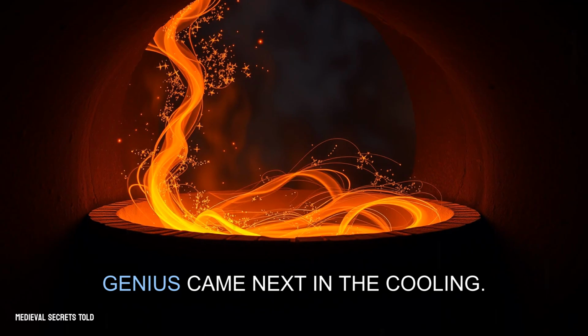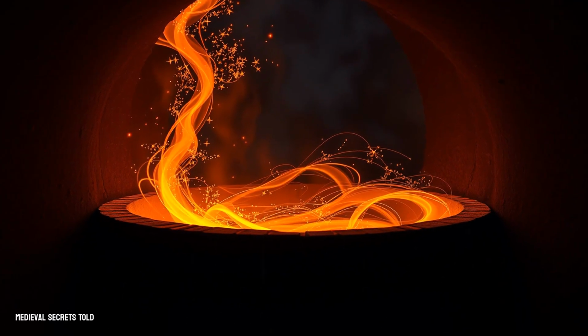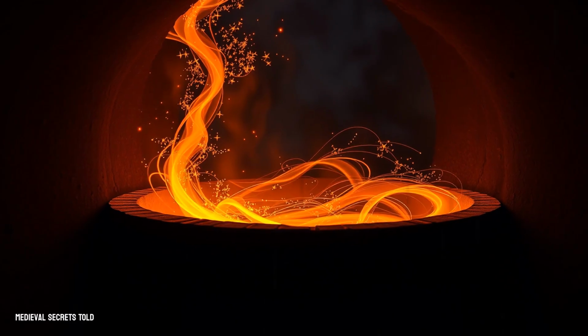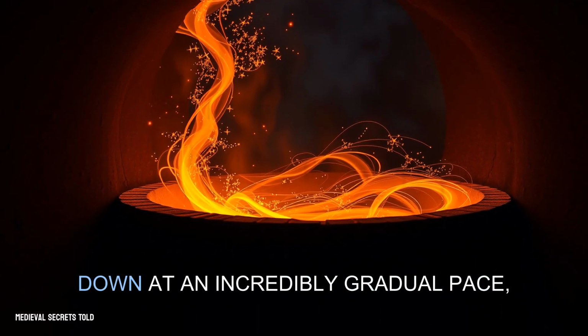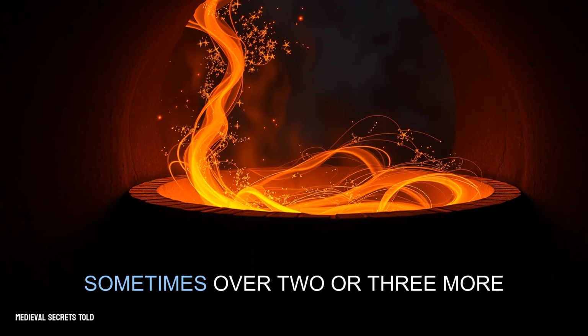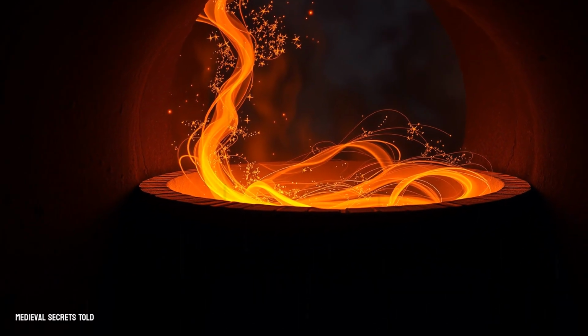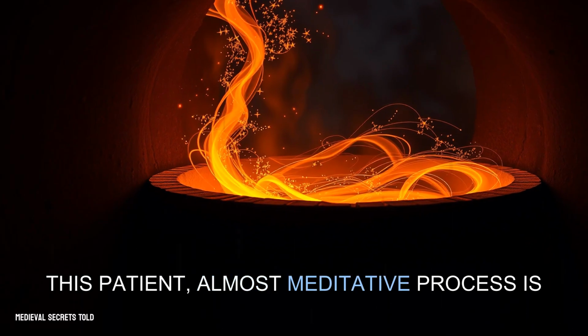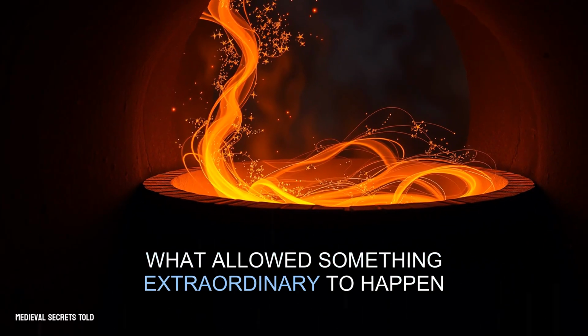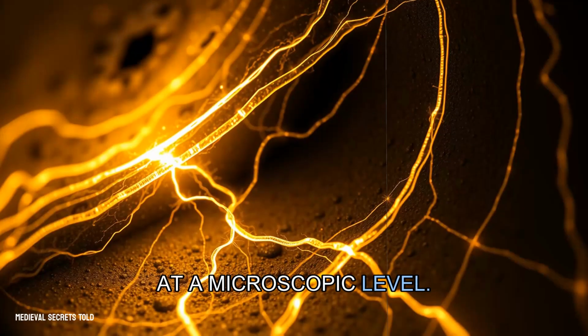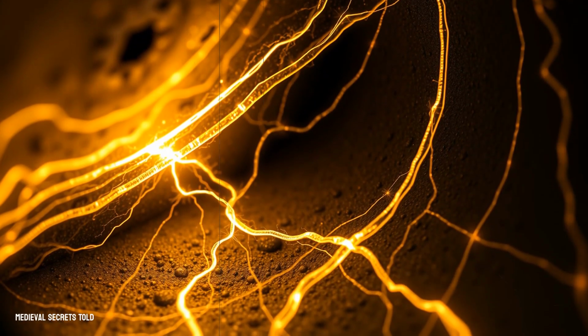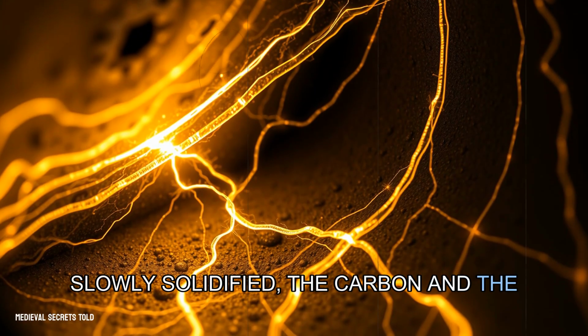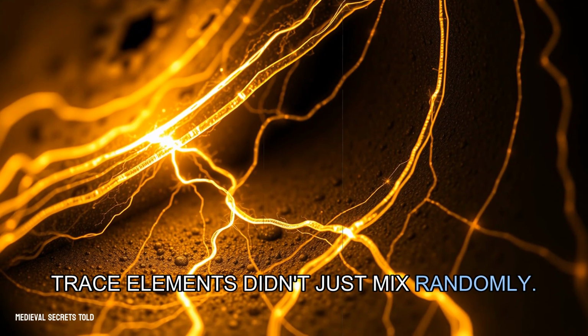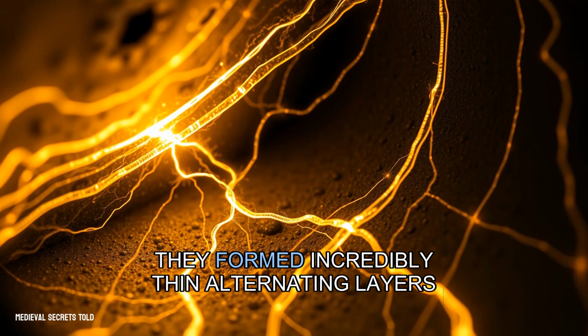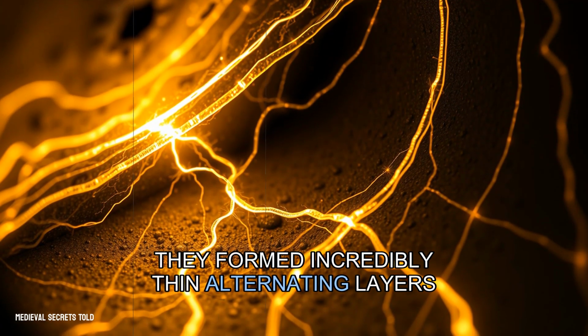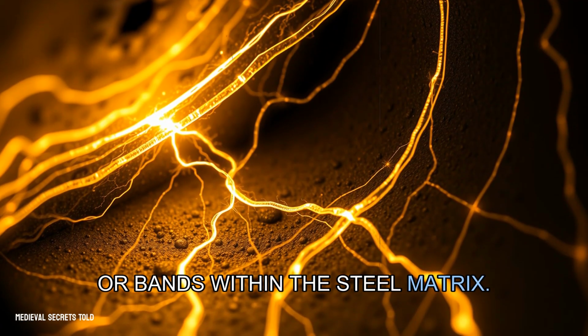But the real genius came next in the cooling. They didn't quench it or cool it quickly. They let the entire crucible cool down at an incredibly gradual pace, sometimes over 2 or 3 more days. This patient, almost meditative process is what allowed something extraordinary to happen at a microscopic level. As the molten soup of metal slowly solidified, the carbon and the trace elements didn't just mix randomly. They organized themselves. They formed incredibly thin, alternating layers or bands within the steel matrix.